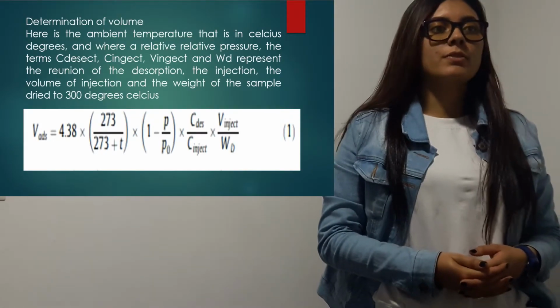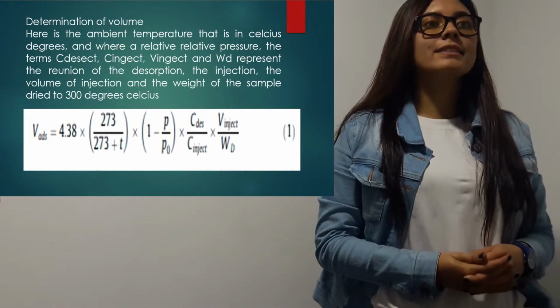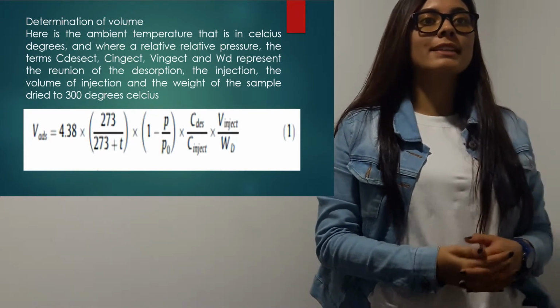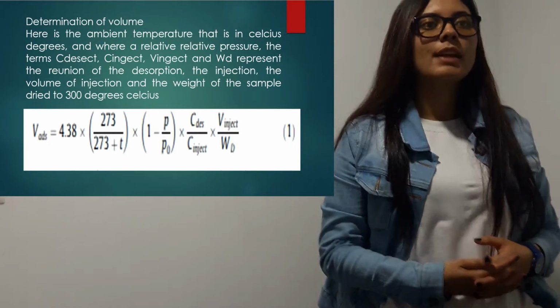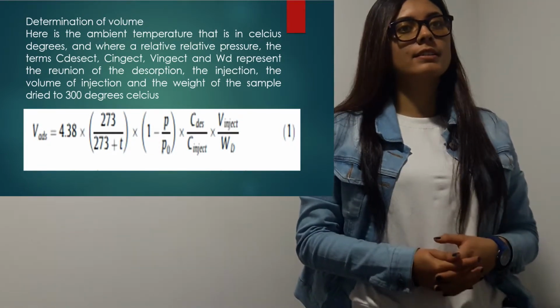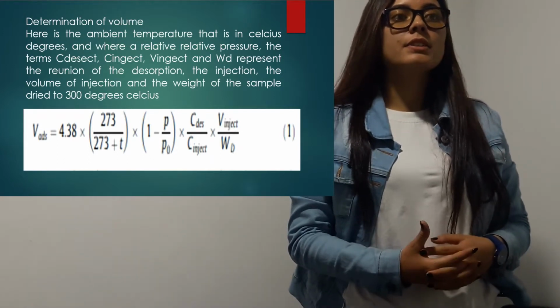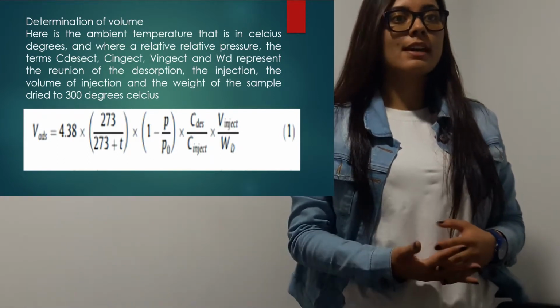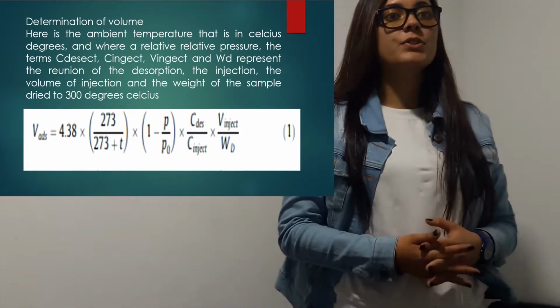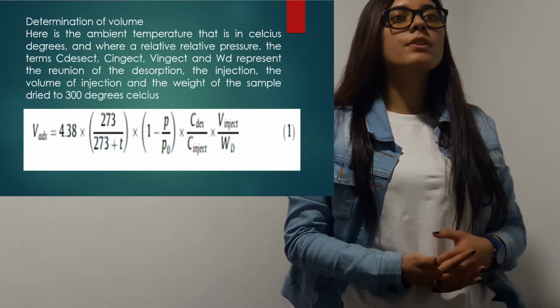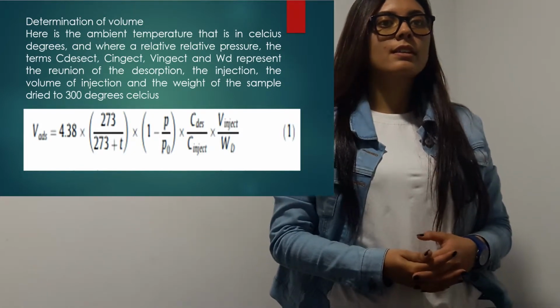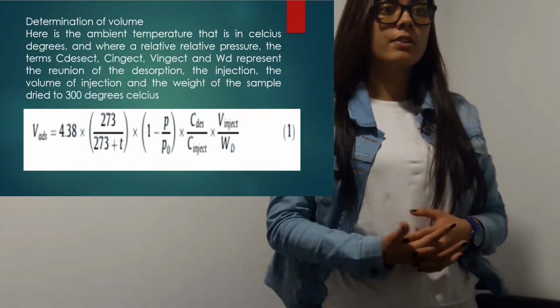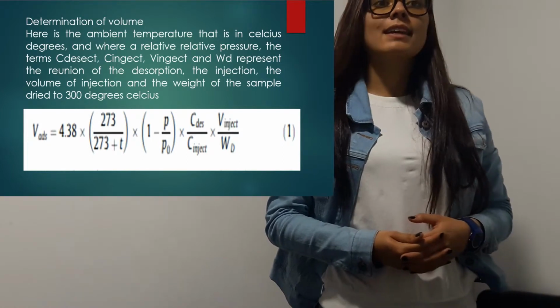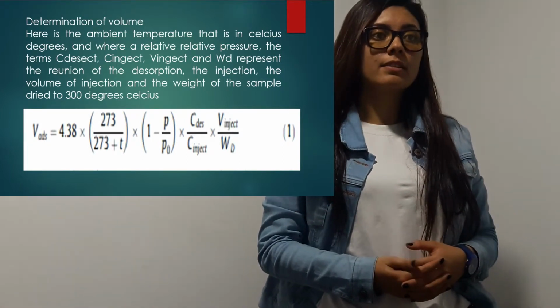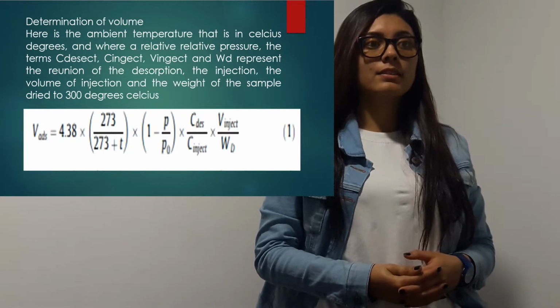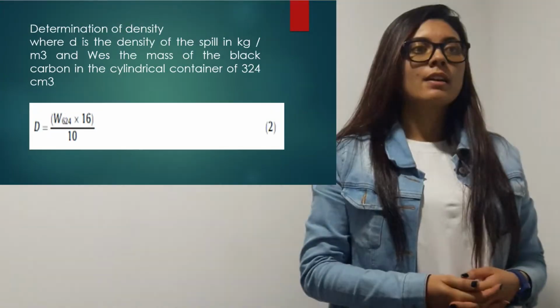Determination of volume. Here is the ambient temperature, that is Celsius degrees, and here are the relative pressure, the terms Cdes, Cinject, Vinject, and Wd represent the desorption, the injection, the volume of injection, and the weight of sample dried to 300 degrees Celsius.